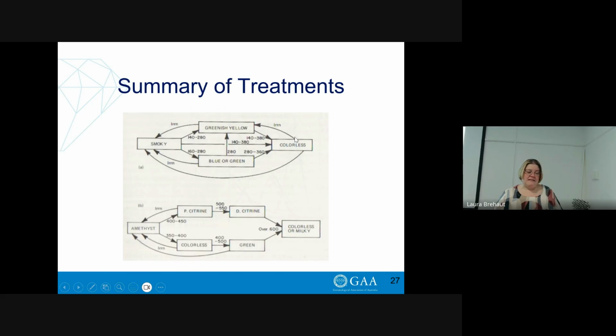Interestingly, if you start out at colorless and you irradiate colorless, you usually derive a smoky color. That's because smoky quartz is a color center associated with aluminium. So you've got silicon, oxygen, and a small amount of aluminium. None of those elements are transition elements, and colorless quartz may contain enough aluminium as a whole precursor or a trapped precursor, so that when it's irradiated, it actually acquires a smoky color because of the aluminium in the quartz.